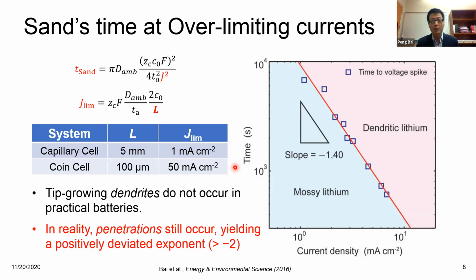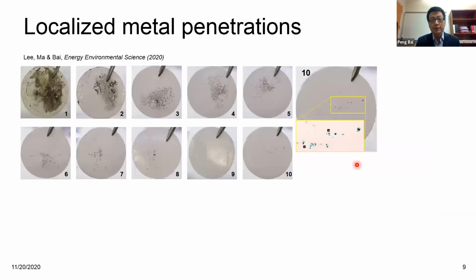And not only that, when you look at the slope, it's not strictly -2, not only for the capillary cell, but also for many other practical coin cells. People always find this -1.5 or -1.4 slope. What's the reason for that? There are really two questions we need to handle. First, why does penetration still happen when the current is lower than the limiting current? Second, when this penetration happens, why does the characteristic time versus current density give an exponent larger than -2?